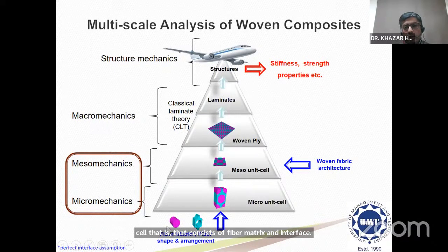So theoretically, we can say these fiber, matrix, and interface cover all kinds of composite structures. So these are the basic building blocks. If we know the fiber, matrix, and their interface properties, then we can estimate the properties of this meso-unit cell representing the woven plies with the help of woven geometrical parameters. And once the ply elastic properties are known, we can estimate the laminate response with the help of classical laminate theory or some other methods. And finally, we can estimate the stiffness response of a structure.